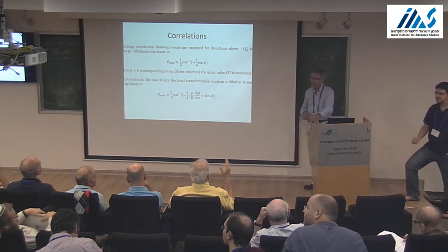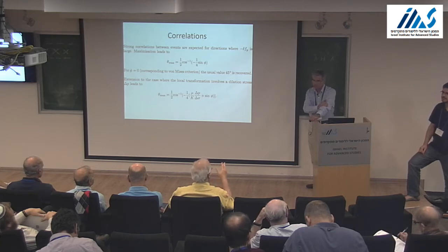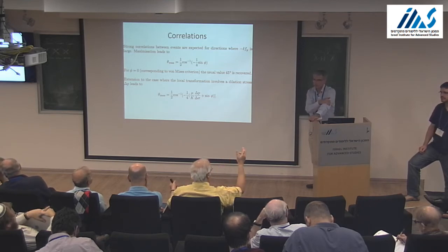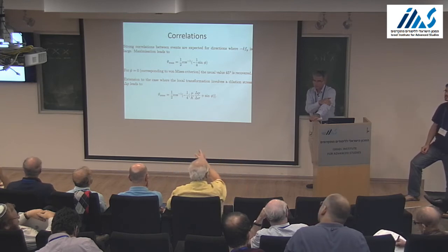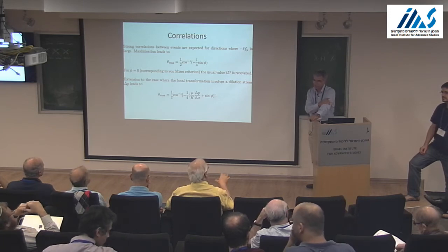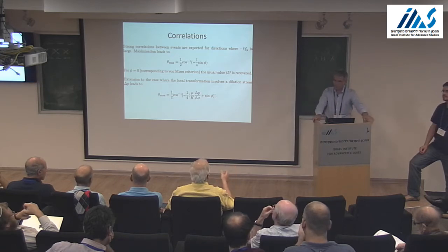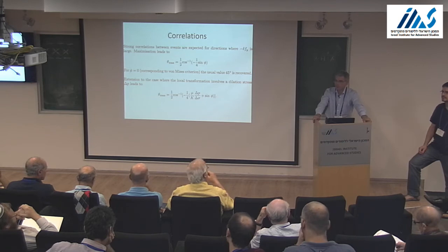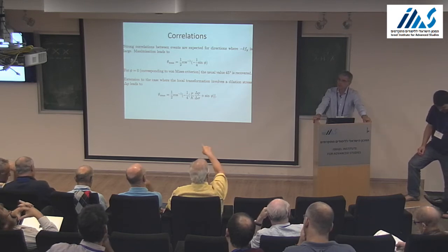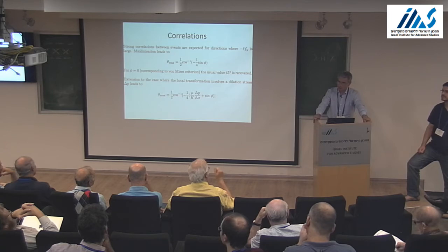It's a lot of work. I still want to raise some doubts about the pure applicability of the elasticity theory to granular frictional systems. We are running simulations, and you see there are all kinds of catastrophes. You have those force chains, and they suddenly break into a new force chain arrangement, which is not at all actually measurable. And you have many frictional local events, rotation, and when you cross the yield limit locally, then Coulomb law. So I'm not sure that all the events can be put into this picture, and one has to think carefully. I'm not sure that the simulations you show that already take into account this formulation will be in full agreement with actual granular simulations with friction. I think one has to be careful with this.